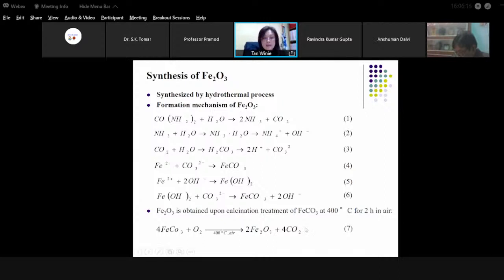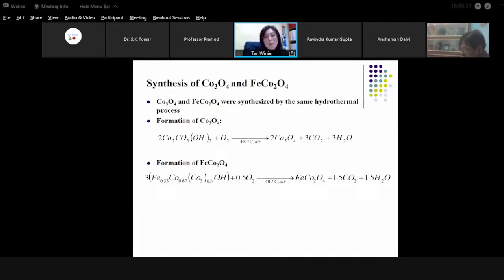Iron oxide can then be obtained upon calcination of this iron carbonate at 400 degrees Celsius for 2 hours in air. Cobalt oxide was synthesized using the same procedure, except that we substitute the iron chloride tetrahydrate with cobalt chloride hexahydrate. During the hydrothermal process, the cobalt reacts with the carbonate and hydroxide from the decomposition of urea to form cobalt hydroxyl carbonate. This is the precursor for cobalt oxide. The cobalt oxide is then obtained after calcination of the cobalt hydroxyl carbonate at 400 degrees Celsius in air.